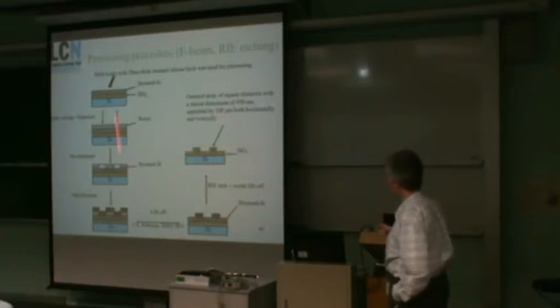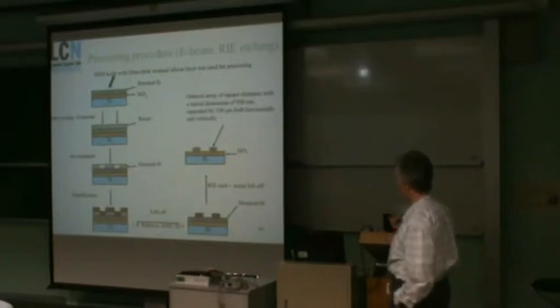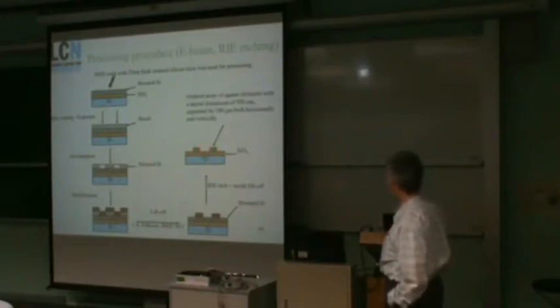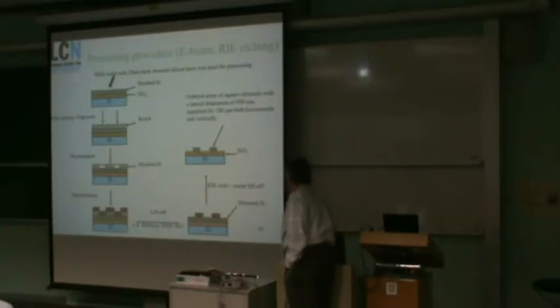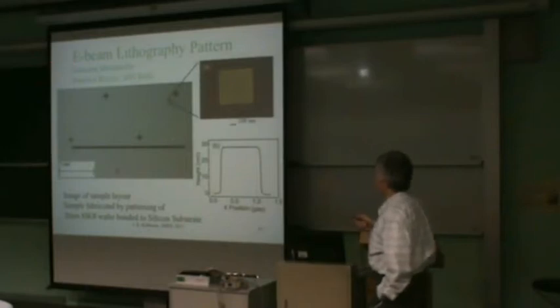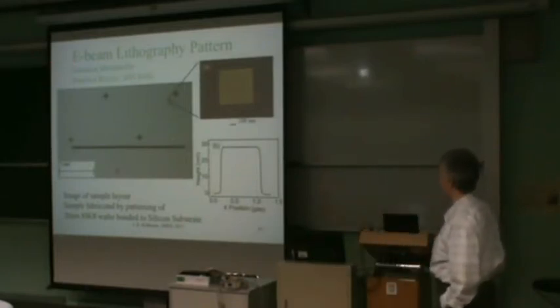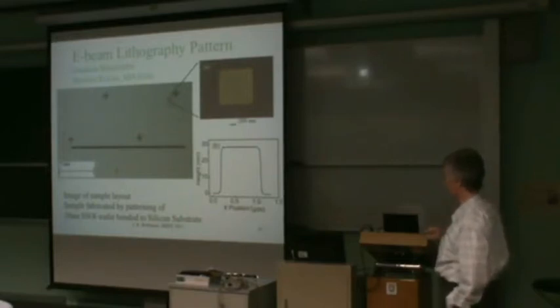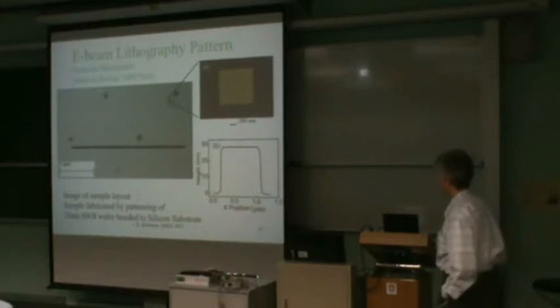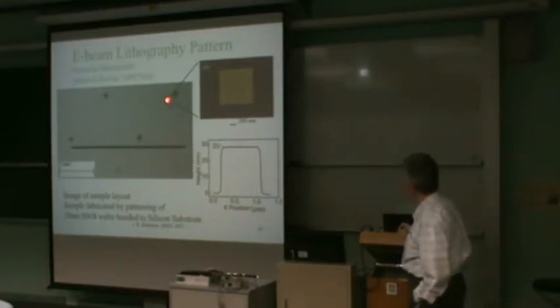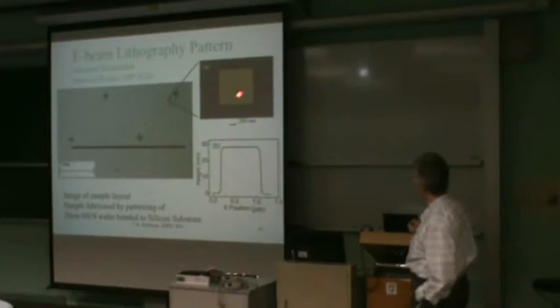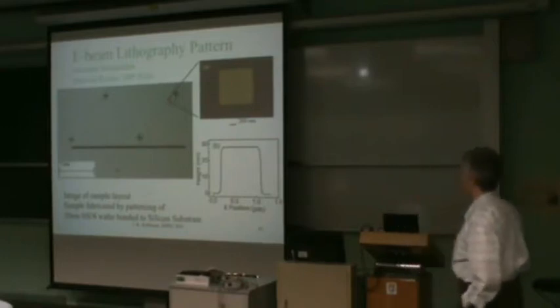So this shows the method developed to write patterns onto the wafer. Using lift-off methods and reactive ion etching, we can generate a pattern structure of strained silicon on insulator, which is the thing we looked at in the X-ray beam. The collaborators, Usama and Manfred at MPI Halle, did the wafer bonding and the lithography. So what we made were little squares of strained silicon on insulator. There are markers so that we can find them. Here is an SEM picture of a square, and you can see it's a 1 micron square.